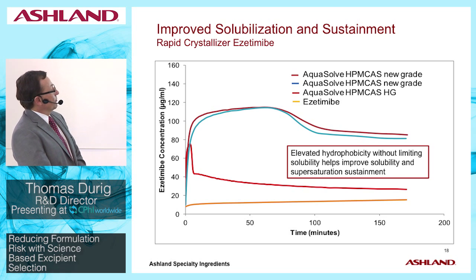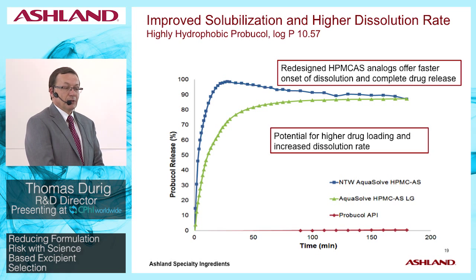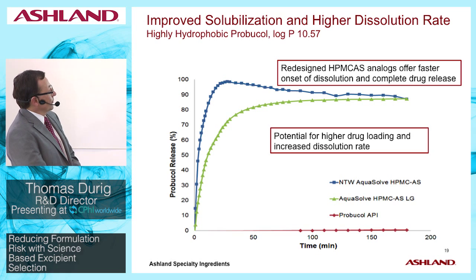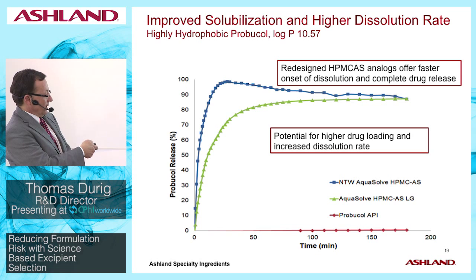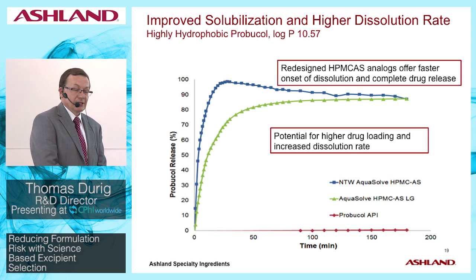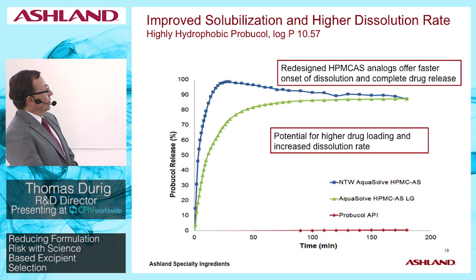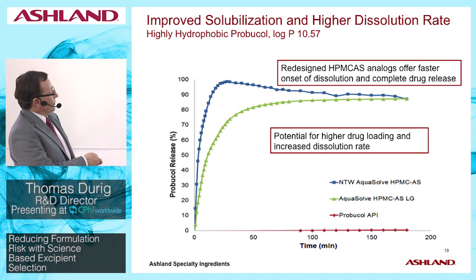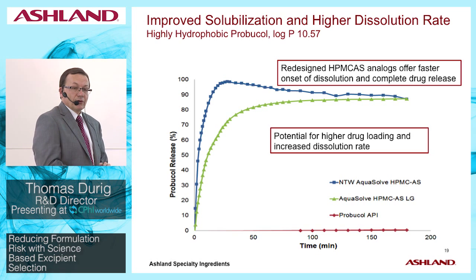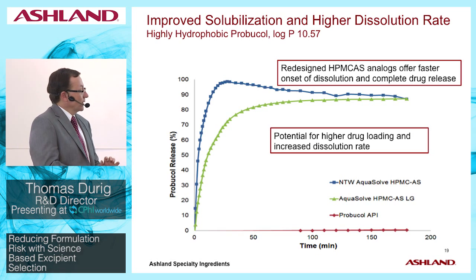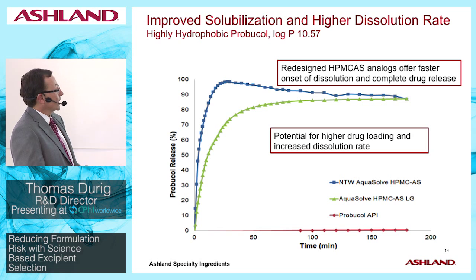Then the last example here is for very highly hydrophobic drugs. There are drugs which are extremely hydrophobic, with very high log Ps. In this case, we're using Probucol as a non-proprietary example of a high log P compound that has a log P of 10. And as you can see here again, our new analogs of HPMCAS are able to achieve significant improvement in terms of solubilization over the currently available HPMCAS.